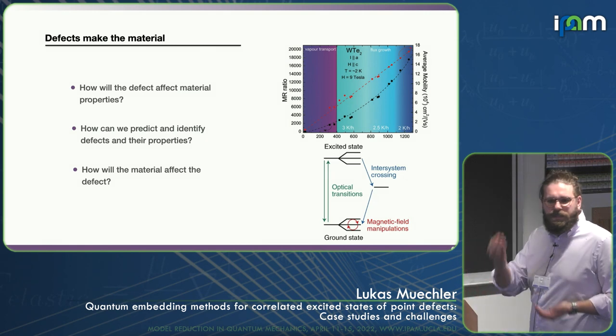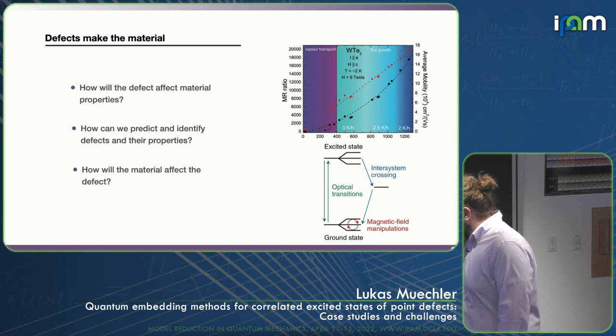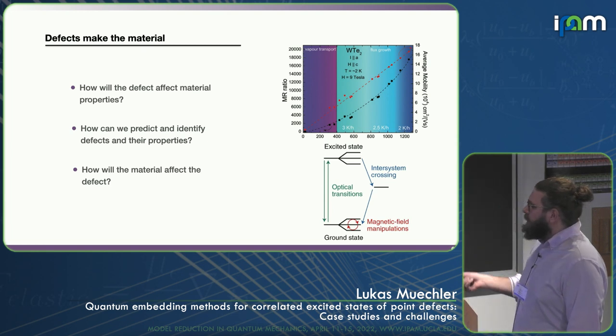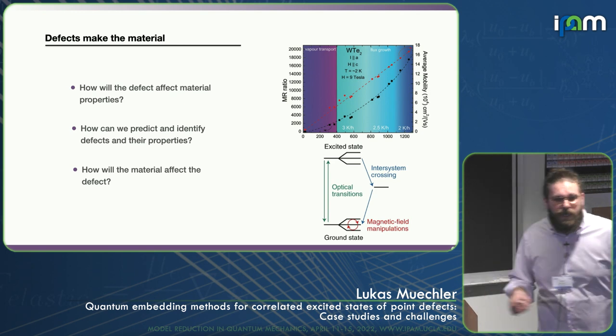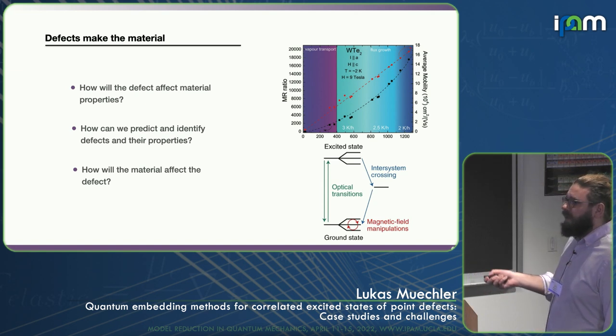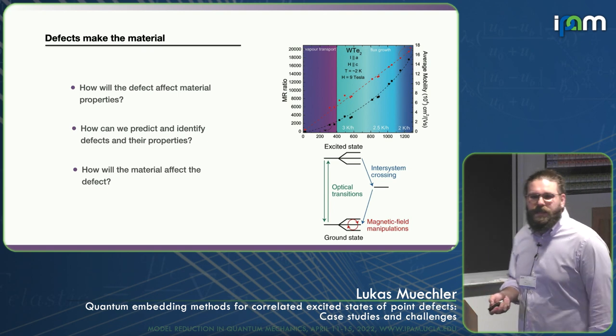What's different about the defects I'm going to talk about today is that we're not going to ask how the defect affects the material. We're going to ask how the material affects the defect. It turns out that these discrete defect states, partially inside the band gap, can also be resonances in the bands. Many of these defects have some sort of ground state and then an excited state, and the ground state is often spin polarized. One can then ask: can we understand the optical transitions, the excited state dynamics, and so on?